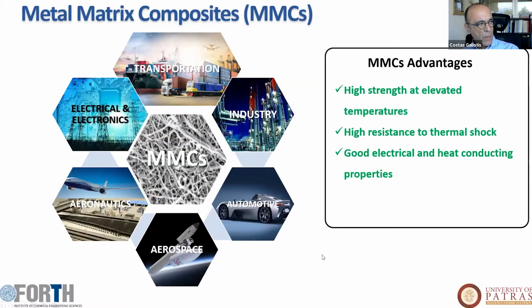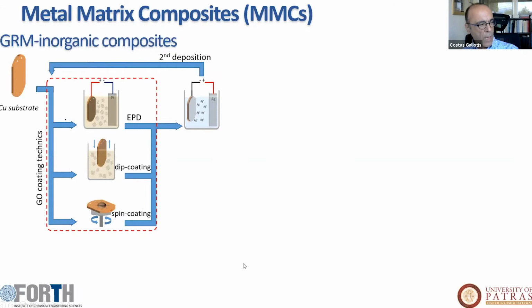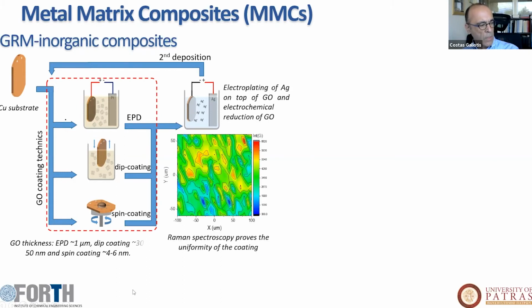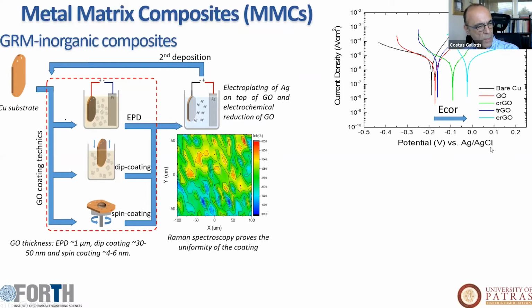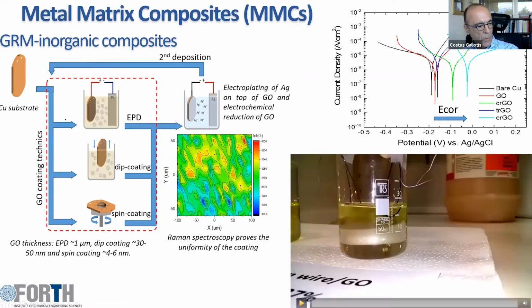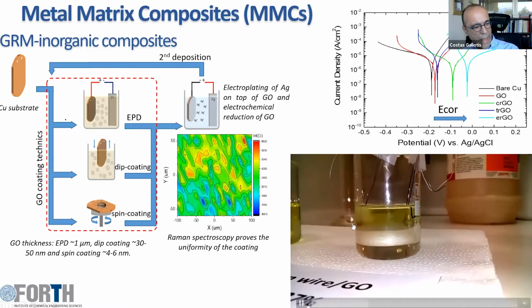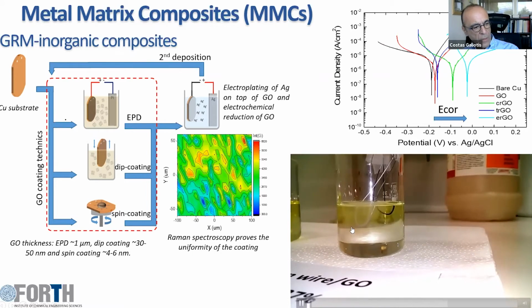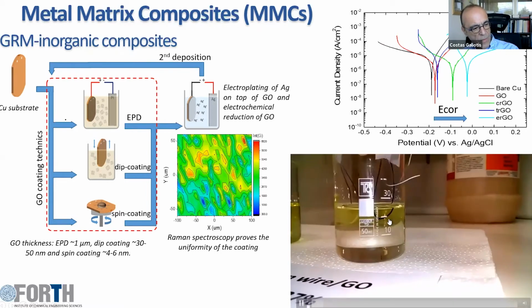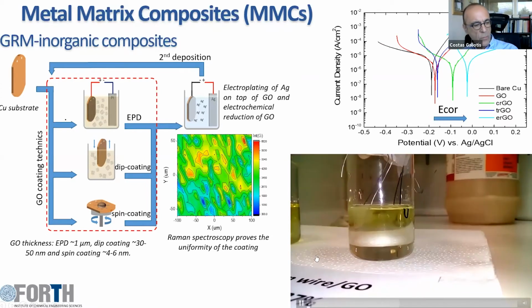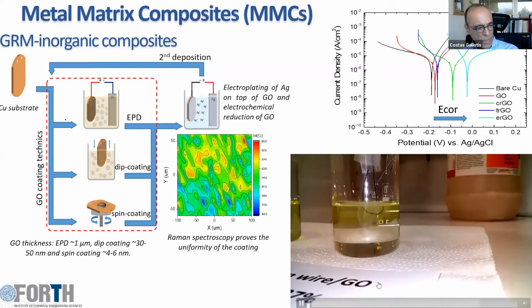And the final thing is the metal matrix composites, which I promised at the beginning. Here we look at the corrosion resistance. We can cover the metallic structures with either electroplating, dip coating, or spin coating. And of course, we have different thicknesses of graphene layers and coatings on these metal plates. We will see that the corrosion resistance moves the potential to positive values. The corrosion resistance is much better. And here is an example, which I will play very briefly. You will see this is a steel wire in hydrochloric acid, and of course, it completely dissolves the wire into the acid. The black one is the same steel wire covered with graphene, and nothing happens to it after hours in concentrated hydrochloric acid.